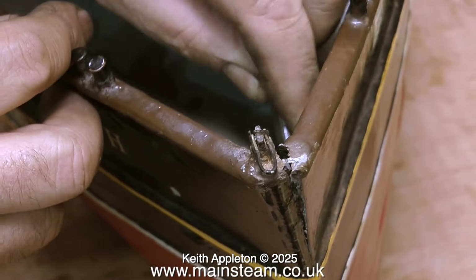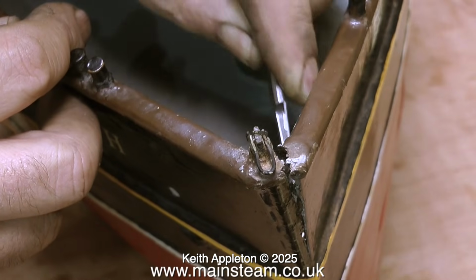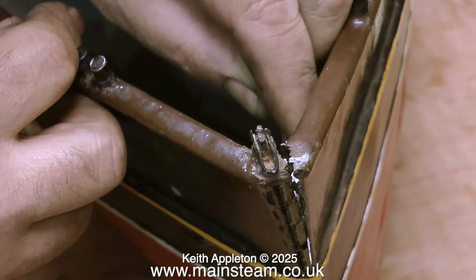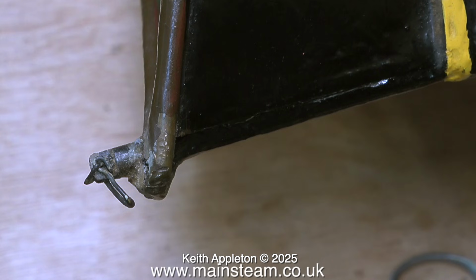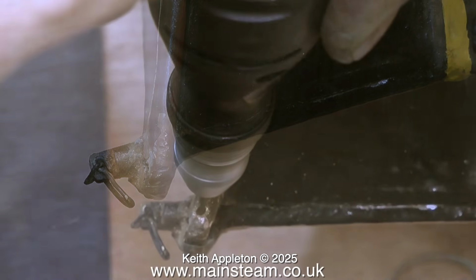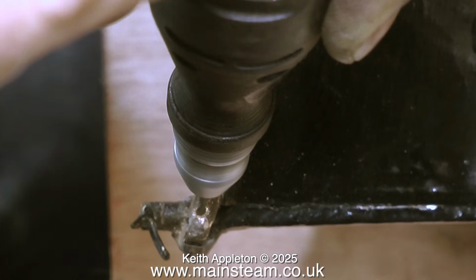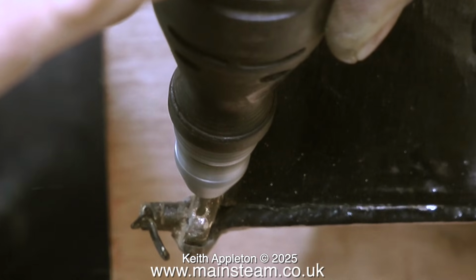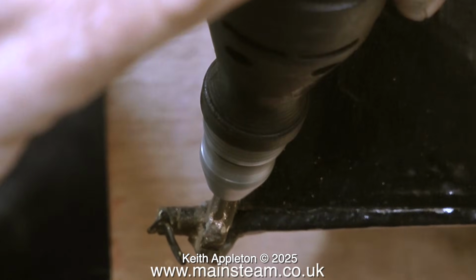There has been an attempt to repair this in the past using some filler, which wasn't very well done and it wasn't successful. I've dug out all of the filler, every trace of it, so now at least I have some clean metal surfaces that I can stick back together. A shape like this is quite difficult to clamp, and besides it wouldn't be permanent. The coaming around the top edge of the hull, the part that's painted brown, is made from brass, and the main support for the bow is also made of brass.